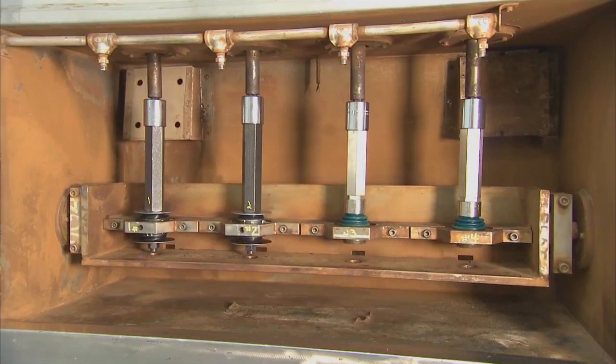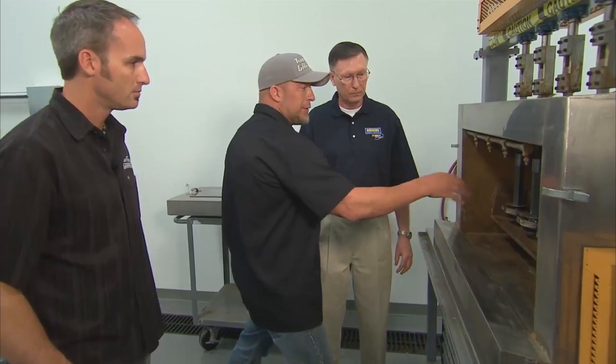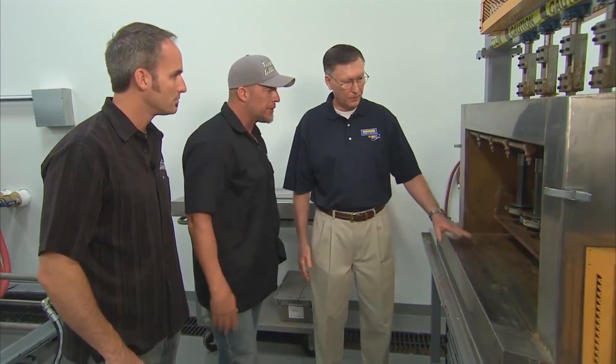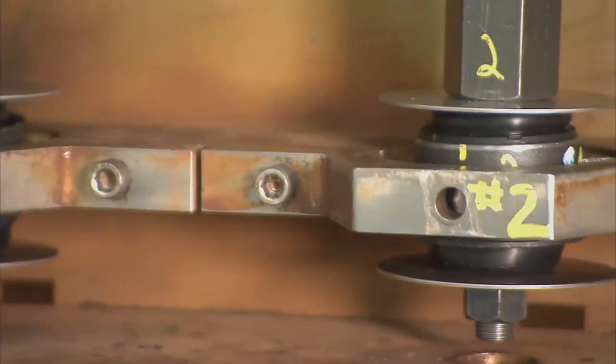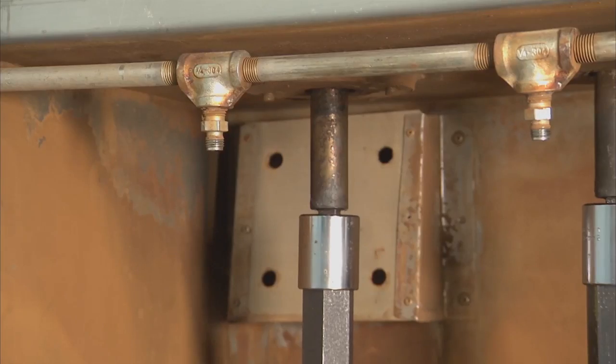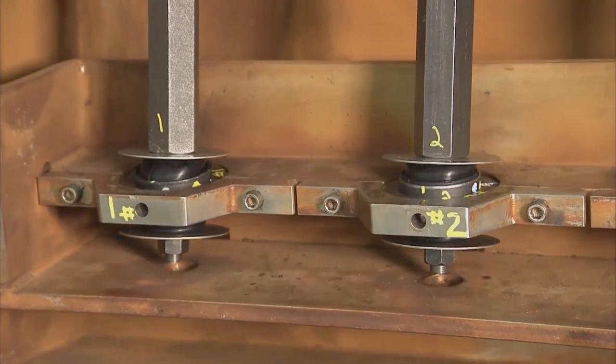Well, here's the boot tester. And this is another level of detail that we go through, we make absolutely sure that the boot seals every time. Yeah, you can see the discoloration in it, so obviously you get it really hot, you probably hit it with some cold and so forth, see the nozzles for some moisture or something. This thing runs from minus 45 below zero to 140 degrees, and we're trying to make sure that everything stays intact and sealed through that whole temperature range, because you can get splits. You put salt spray in there? Yes. We add a grit and salt spray, so if there's any penetration, you'll see it inside the boot. So you can get a real-world test environment in there, and you see all the extremes to make sure that part's going to last.